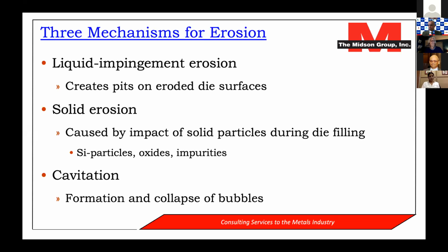Then a third mechanism for erosion is cavitation. Cavitation is a special type of erosion. This is when we get the formation of small bubbles as the liquid metal is filling the cavity, and then the bubbles collapse at very high velocity and very high pressures against the surface of the die and can cause quite a large amount of damage. And often we see this more in zinc die casting dies, not because it's more important in zinc, but some of the other mechanisms that we've talked about, such as heat checking and soldering, are less important in zinc die casting, and therefore we see the effect of cavitation because often the zinc die casting dies last a long time.